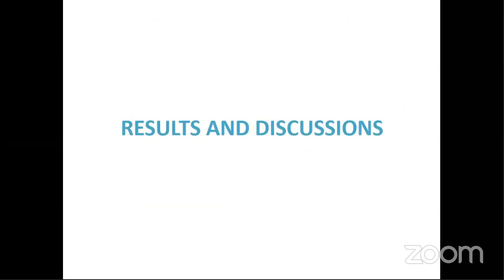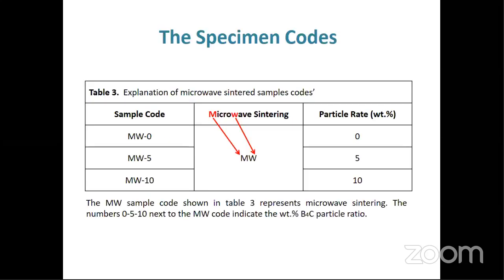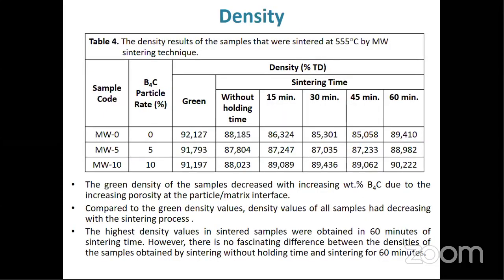The experimental results were discussed in this section. The MW sample code shown in Table 3 represents microwave sintering. The numbers 0, 5, 10 next to the MW code indicate the percentage by weight boron carbide particle ratio. Density values corresponding to produced and sintered samples are as in Table 4. The green density of samples decreased with increasing percentage by weight boron carbide due to the increase in porosity at the particle matrix interface.